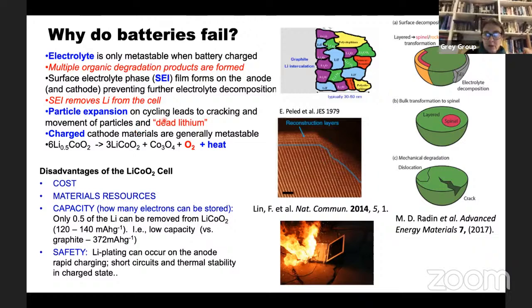And then you have this idea I talked about before, that particles expand and contract, and they can crack, and so you can lose electrical contact. Or there's another idea that when you make a material, it's typically made in its stable thermodynamic state. But when you charge it, in this case, you take lithium cobalt oxide and you pull out 50% of the lithium, this material is no longer thermodynamically stable, it's metastable, and it's metastable towards a cobalt oxide and generation of oxygen and obviously heat. And it's that oxygen then that can react with the organic electrolyte and cause these fires.